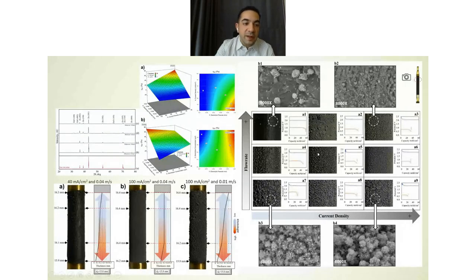The paper also discussed the effect of gravity on the morphology. As you can see, mostly in all cases, either by changing the flow rate or current density, the deposition thickness on the bottom of the rod is thinner than the top of the rod, except when we use high current and high flow rate. So this morphology here is indicating the one on the top right on the previous figure. And the paper also tried to optimize the round trip efficiency of the system, while the optimal values are incorporated into the operation of the zinc battery.